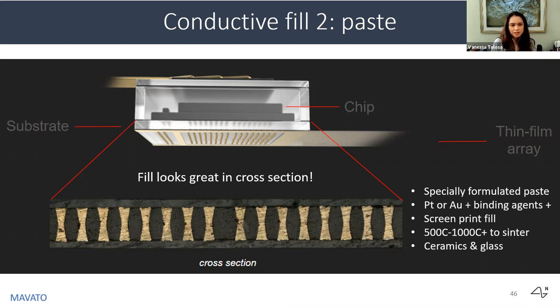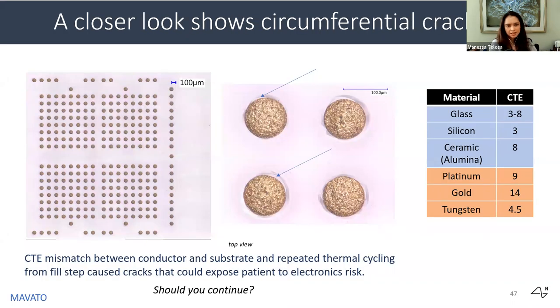It's great. The process is harsher than plating, but in the same amount of development time, your vias already look much nicer. But then you look at the substrate from another view and you find cracks around the vias. And hermeticity testing confirms your fear. Liquids are able to get through the cracks. You suspect that this comes from the CTE, or coefficient of thermal expansion, mismatch between your conductor and your substrate. Because with this process, there is a lot of thermal cycling happening at very high temperatures.